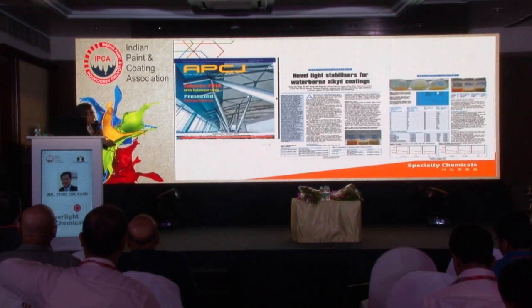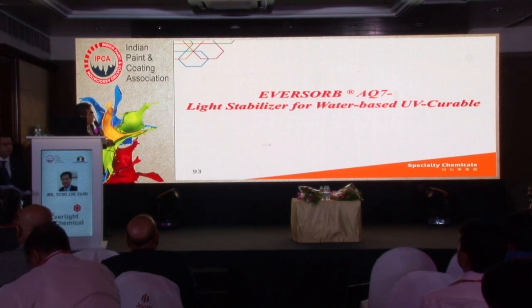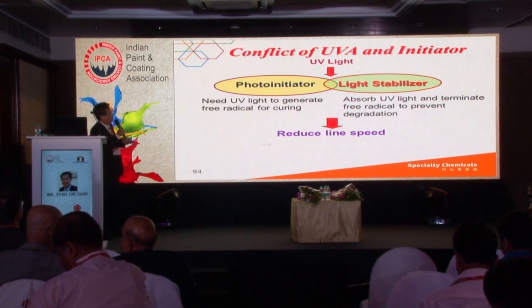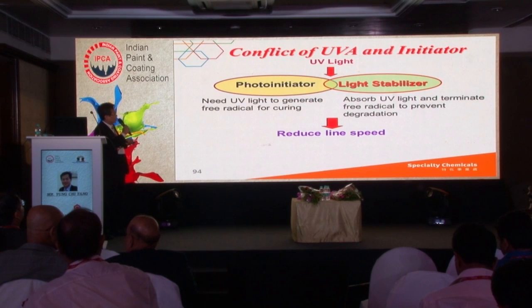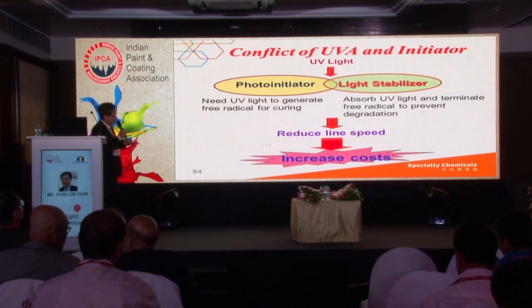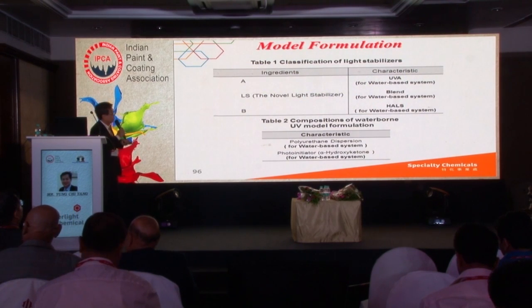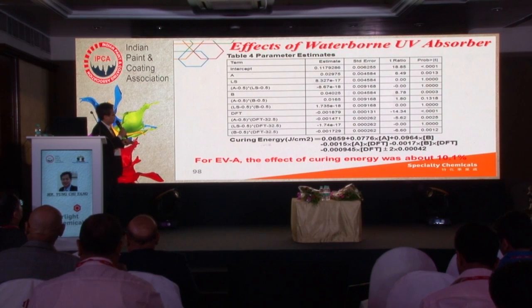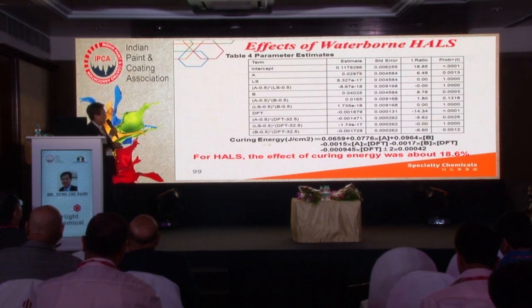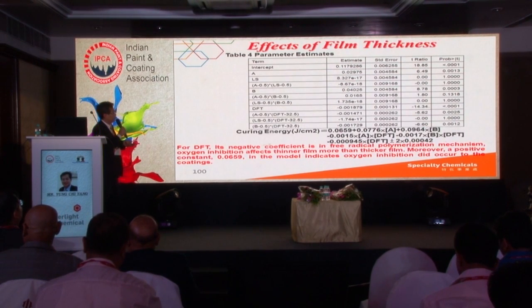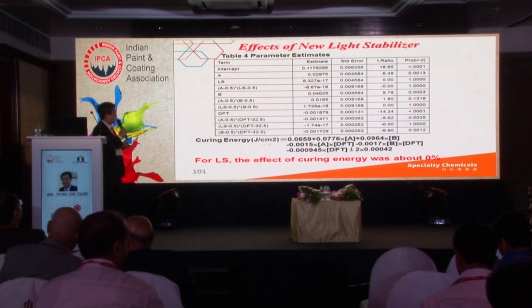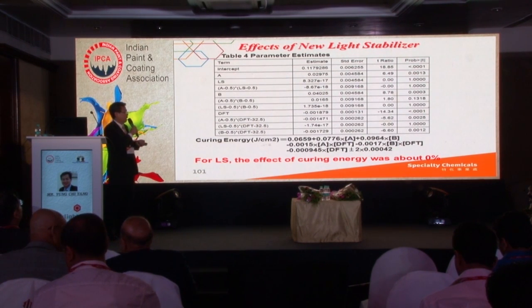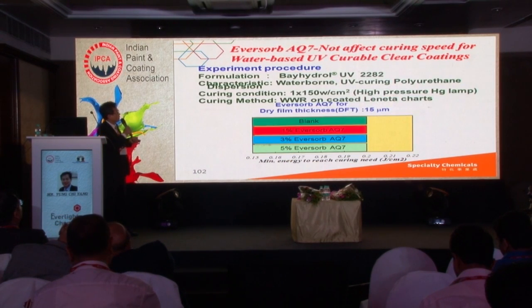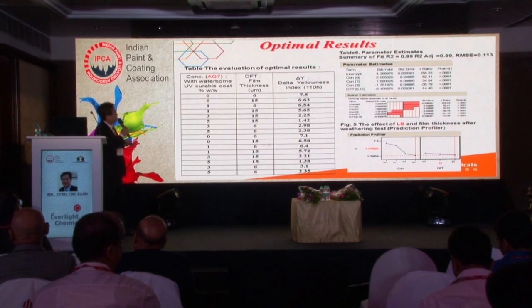So finally, the AQ7 UV curable. We know the complete UV absorber and initiator, photoinitiator and light, will have some problem used together. So this shows you we use DOE to find the curing energy. You can see the UVA effect of UV energy was about 10%. The HALS maybe 18.6%. And dry film thickness is negative because of the different film thickness. And for our new product, the effect of the curing energy was zero. So it's a weathering test with good performance. And from this, you can see the ultimate result is a good performance.